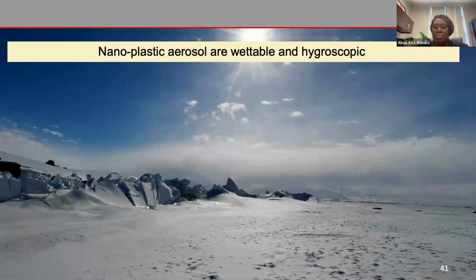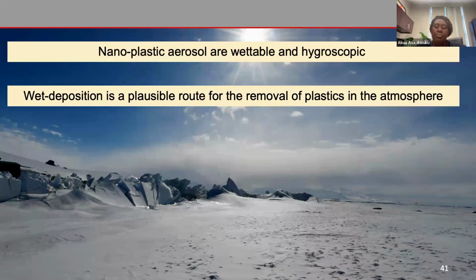So that brings us to some of the conclusions of some of this work, which is that nanoplastic aerosols are wettable and they're hygroscopic. We're able to show that in our measurements, and we're also able to show that now in our predictions, which indicates that wet deposition is actually a plausible route for the removal of plastics in the atmosphere. Originally, when we gathered that freshly fallen snow, we weren't quite sure how these plastics were able to get to such remote areas. But we now see that when we have tiny aerosols that are oligomeric in nature, we can actually have them uptake water and form droplets.